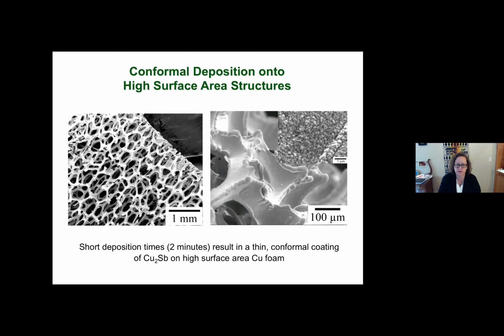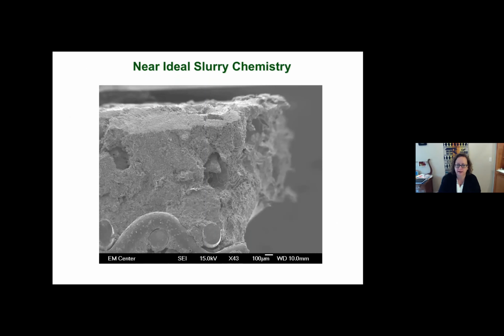So this is what the battery looks like. This is the copper antimonide deposited on the foam. You can see that it deposits faster at areas of high curvature, but it does conformally coat this 3D structure. Once we add all the components, and I'll show you a picture of that in a moment, you do have a freestanding dense 3D battery. This image is showing you the aluminum mesh on the bottom and the cathode slurry dried around that.